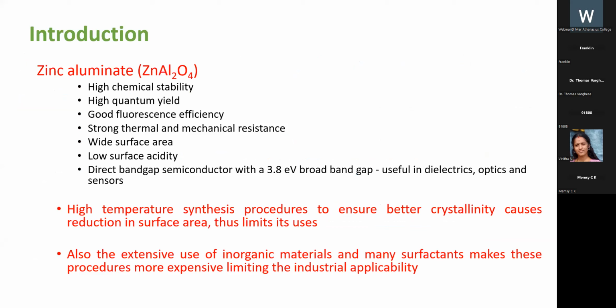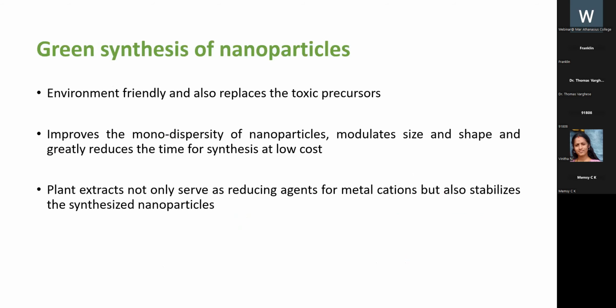Zinc aluminate, the material of the present study, has many advantages like high chemical stability, high quantum yield, good fluorescence efficiency, strong thermal and mechanical resistance, wide surface area, and low surface acidity. It is also a direct bandgap semiconductor with a bandgap of 3.8 electron volt, and it is useful in dielectrics, optics, sensors, and many other applications. But the high temperature synthesis and the use of very toxic chemicals limit its industrial applicability and make it very expensive. Here lies the importance of green synthesis.